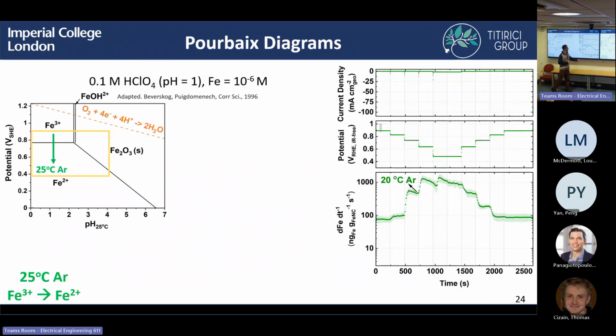And this increase in iron dissolution seems to occur at the potential where we go from iron 3+ to iron 2+. So this is around 0.75 volts. And we see here as we step down past this 0.75 volts, we see this very clear iron dissolution increase. So it seems to be following that as we go from iron 3+ to iron 2+, we have a greater dissolution of iron measured from ICP-MS.